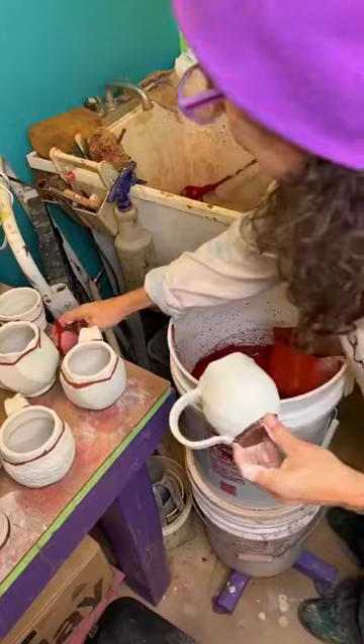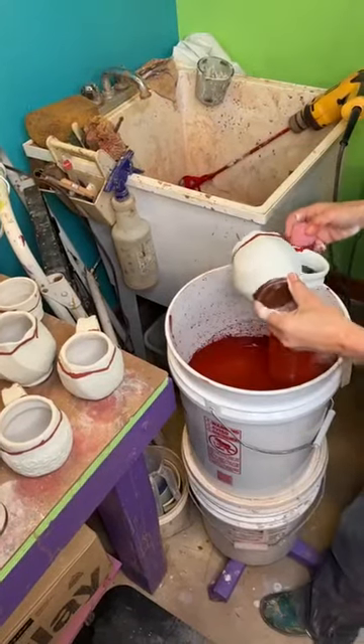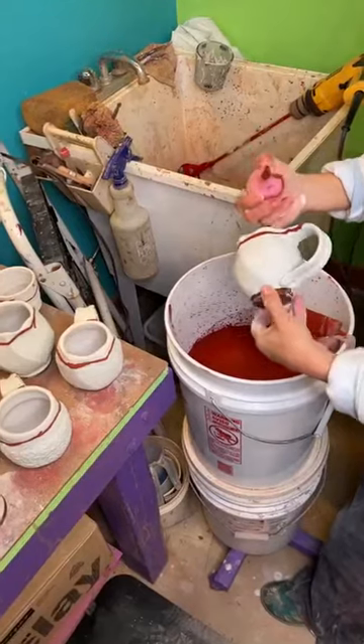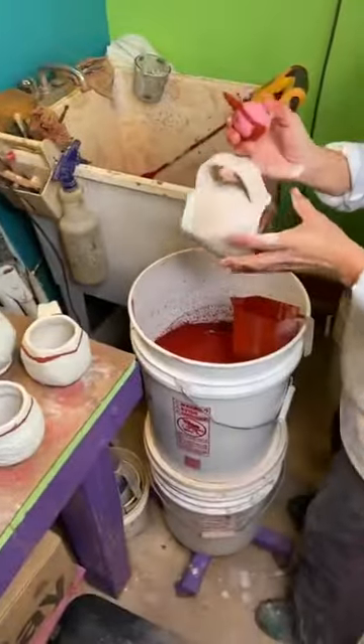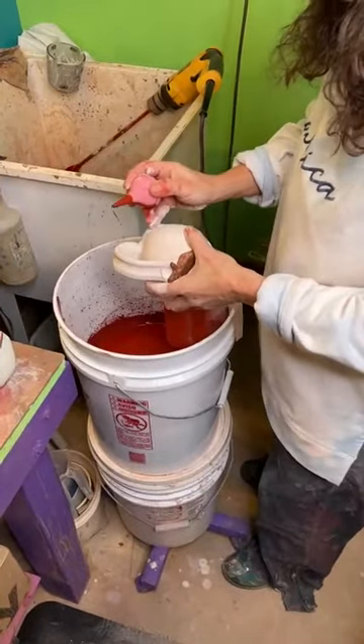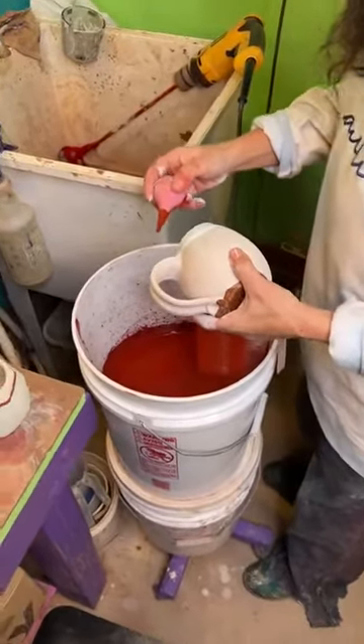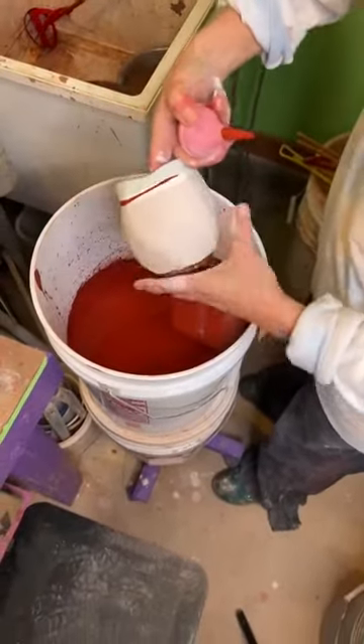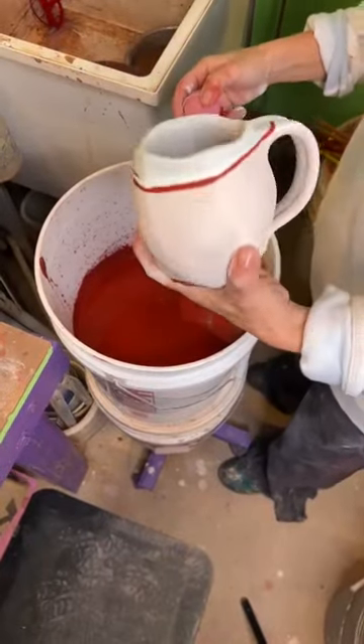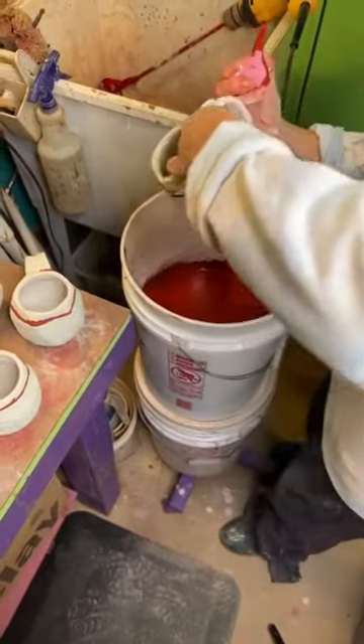It does something kind of magical with that line of glaze. This is a glaze that will already run, but putting another one on really gives it a little oomph. I like using two flux glazes in this way — in combination with other glazes it tends to create flow and runniness. The tenmoku I do use on its own, but the waterfall green I have to actually reformulate — something happened or I lost the original recipe — I can't use it by itself but I can use it this way.